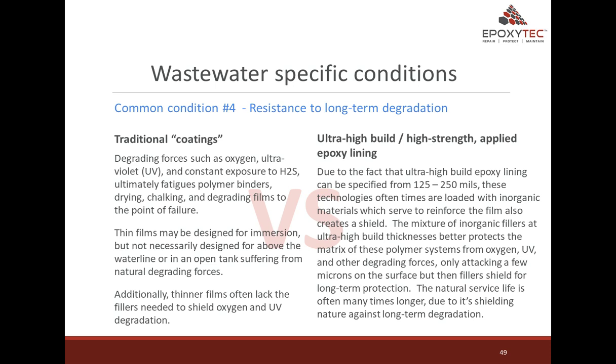Ultra-high build, high-strength applied epoxy lining. Due to the fact that ultra-high build epoxy lining can be specified from 125 to 250 mils, these technologies oftentimes are loaded with inorganic materials which serve to reinforce the film, and also create a shield. The mixture of inorganic fillers at ultra-high build thicknesses better protects the matrix of the polymer systems from oxygen, UV, and other degrading forces, only attacking a few microns on the surface, while the fillers shield for long-term protection. The natural service life is often many times longer due to its shielding nature against long-term degradation.